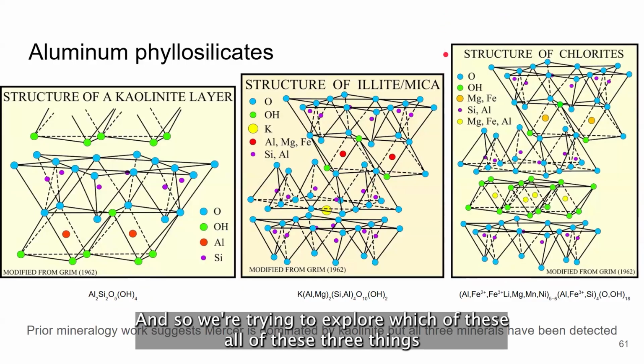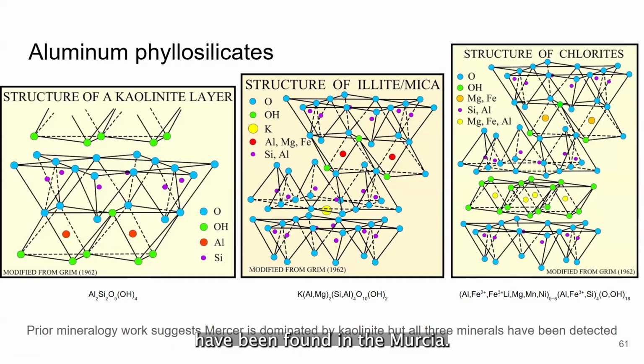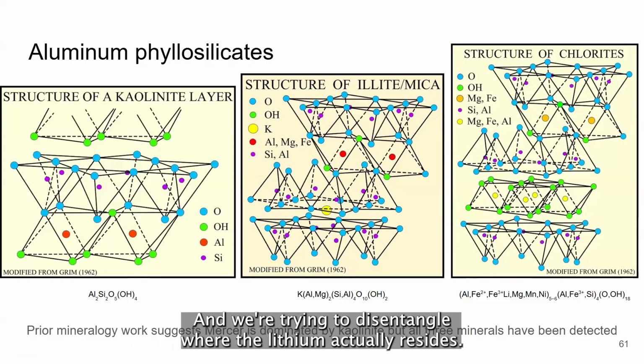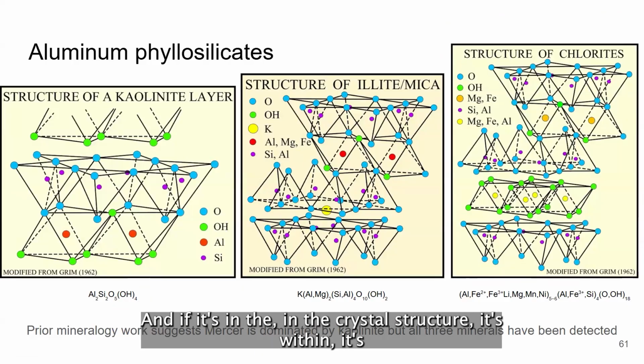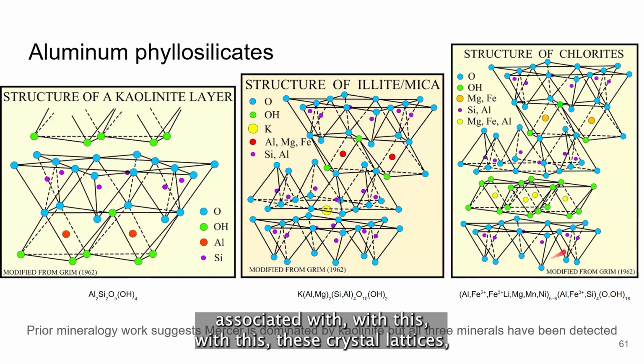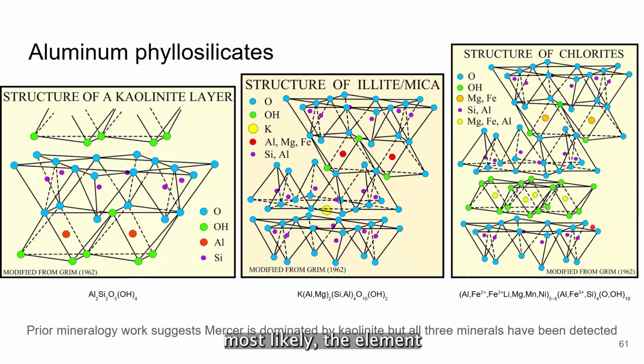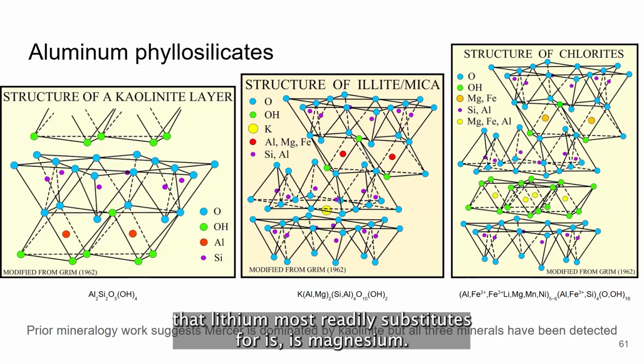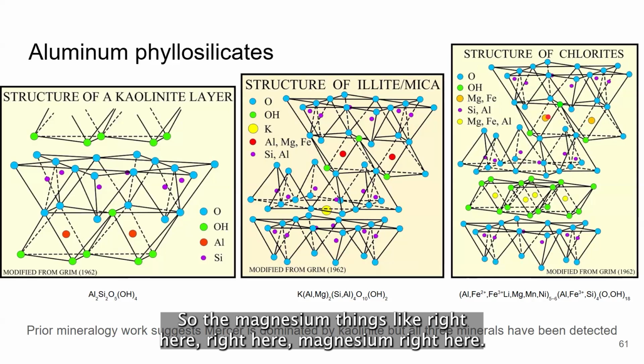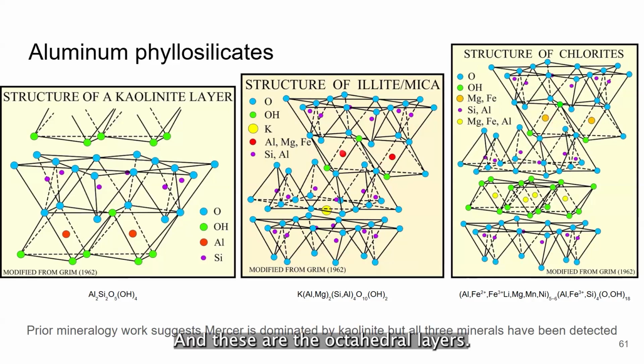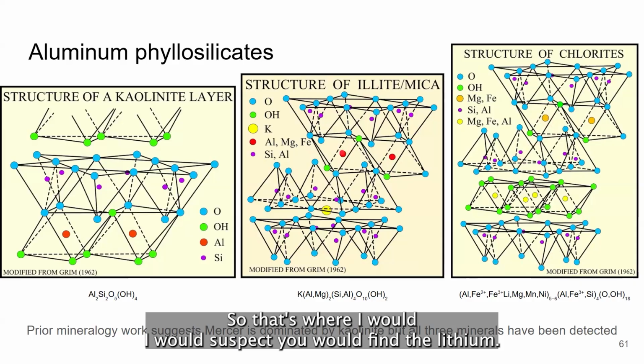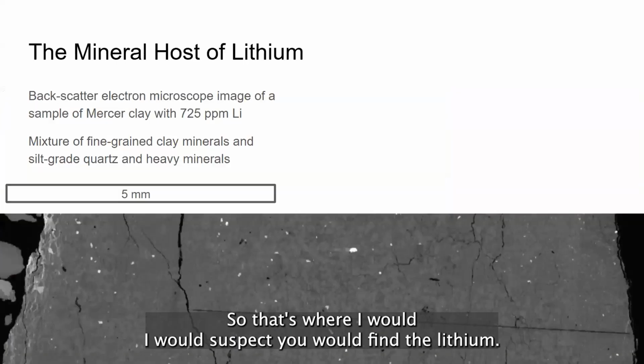All 3 of these have been found in the Mercer, and we're trying to disentangle where the lithium actually resides. If it's in the crystal structure, it's associated with these crystal lattices. Most likely, the element that lithium most readily substitutes for is magnesium. So magnesium is right here, in these octahedral layers. That's where I would suspect you would find the lithium.